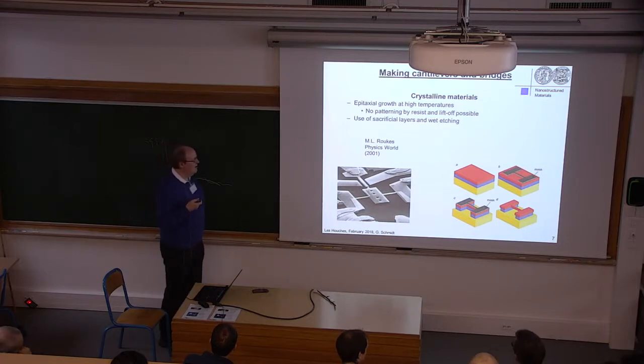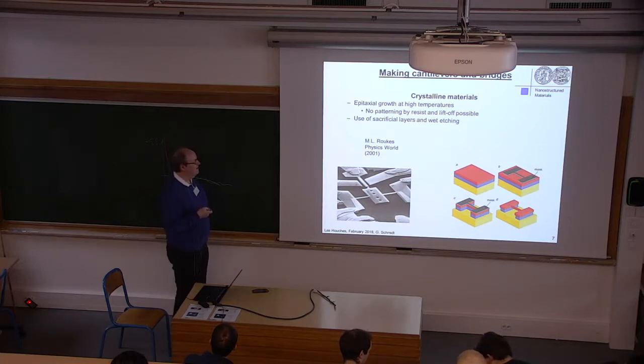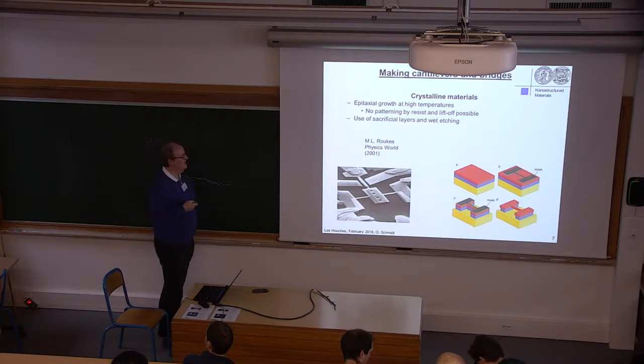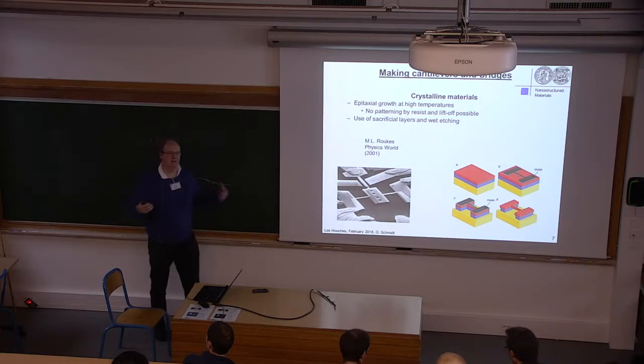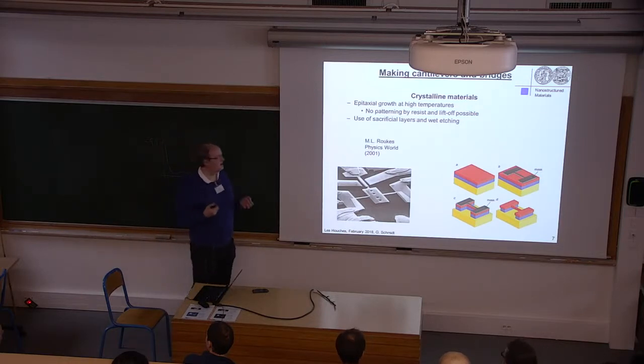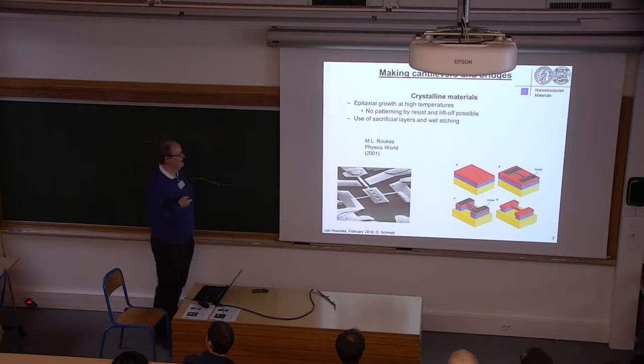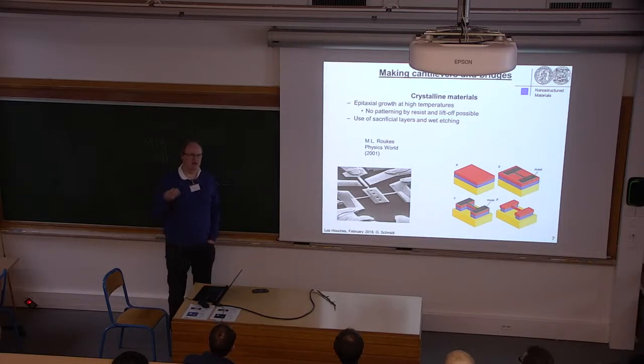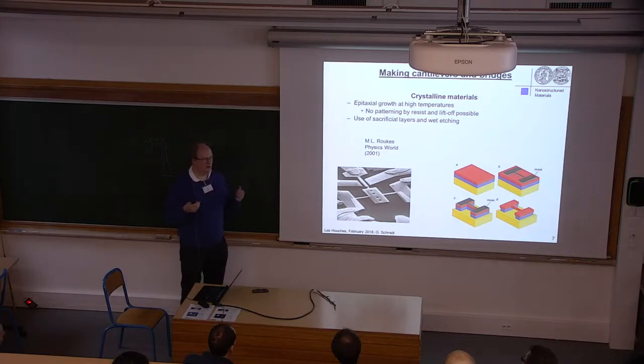But one standard process in principle to make resonators out of crystalline materials, or to make 3D structures out of crystalline materials, is the following. You normally have epitaxial growth at high temperatures. We don't get bulk YIG crystals out of which we want to cut this, but we grow the material. And when you have epitaxial layers, you cannot do any patterning by resist and lift-off, because the resist that you use is normally not stable at high temperatures. You can use some solid state resist or shadow mask, but in this case you have problems removing it afterwards, and to make nice processing you want this.